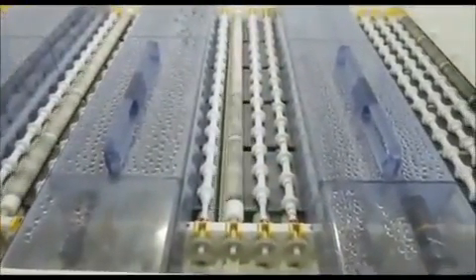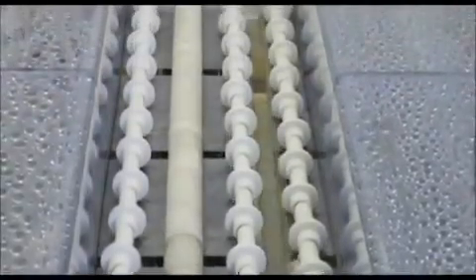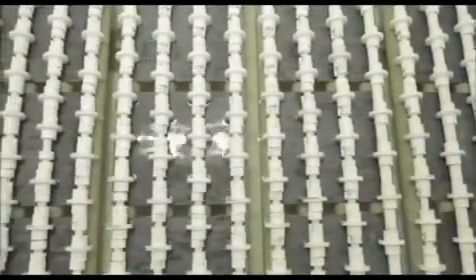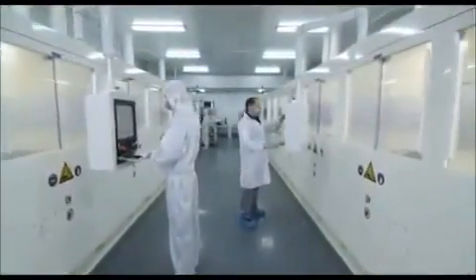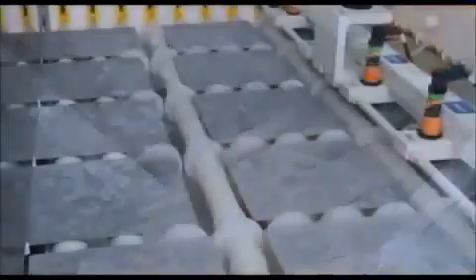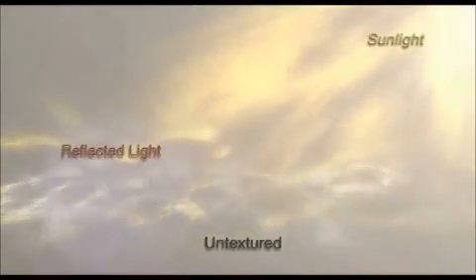The first step in manufacturing solar cells is a process called wet chemical texturing. The wafers are submerged in nitric and hydrofluoric acid baths. This process not only cleans and removes the soiling and the damage that occurs during the earlier process when sawing the wafers, but it also enlarges the surface of the wafer. Then, the isotropic surface texture reduces the sun's reflection on the subsequent surface of the cell.